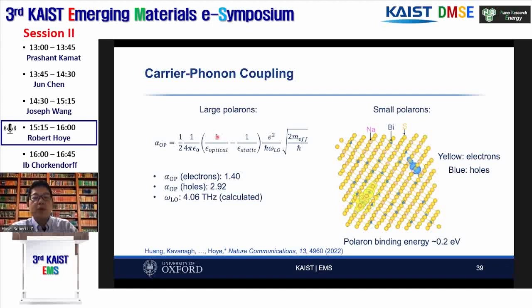So to understand a bit more about what's happening, we calculated the Fröhlich coupling constant, the coupling constant describing coupling between electrons and longitudinal optical phonons. And we found that the coupling constant was in the intermediate range. So it wasn't low, but it wasn't so high that we expect carrier localization either. And in fact, these coupling constants are similar to what you would get in the lead halide perovskites.